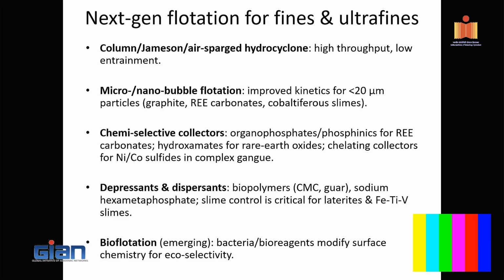Now, in the case of Jameson and microcell, as I said, the generation of the bubbles itself is very fine. Then they have the potential to go for fine particle separations effectively compared to others. And the latest trend coming across, which is still largely in R&D mode right now, is micro and nano bubble flotation. So here the idea is, though the Jameson cell and microcell generate fine bubbles, the moment they come and interact with the liquid or the slurry that is coming, bubble growth happens. And they have only demonstrated in a way where, compared to conventional flotation, you have a better recovery.